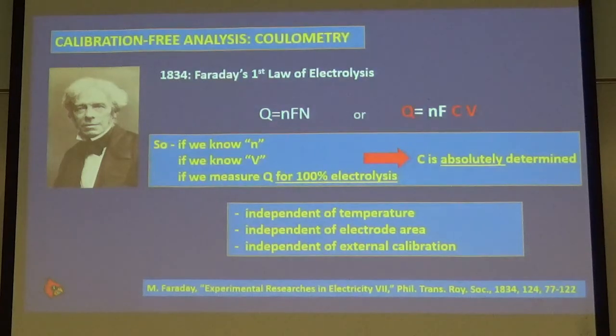Think about a slightly different way to write Faraday's law. Well, the number of moles, that's the concentration, the molarity, times the volume. So this is just another form of Faraday's law. But this tells us that n and F, we know those are constants for any given experiment. Q is what you're going to measure by applying the potential and measuring the current. So that just leaves C and V. Concentration is what I'm interested in. Is the arsenic concentration 10 ppb or higher? So what about V? Well, that's the volume.